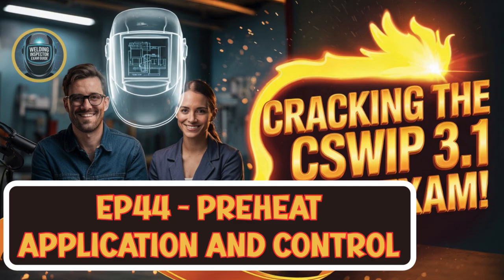These standards tell you how to figure out the required temperatures based on the materials, the thickness, the welding process, and so on. Then those calculated temperatures get validated. They get tested and proven during the formal qualification of the welding procedure. Ah, the WPS, the welding procedure specification. Precisely. And here's the really critical part. According to major qualification standards like EN ISO 15614 or ASME Section 9, both the preheat temperature and the interpass temperature are classified as essential variables.